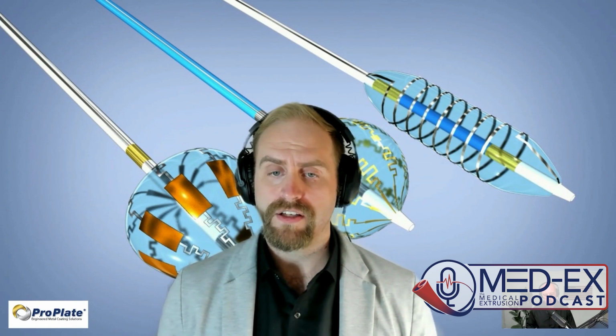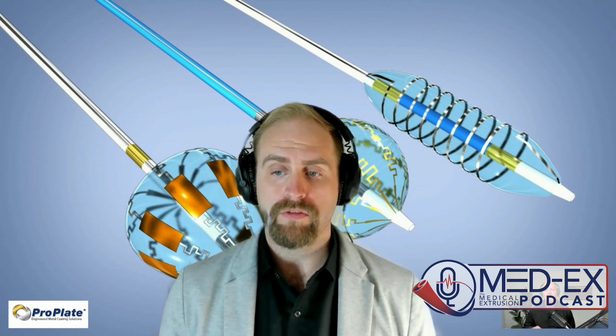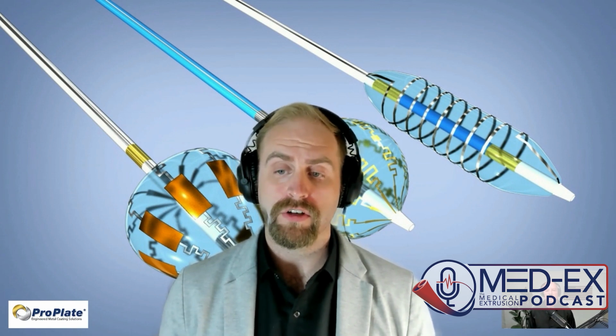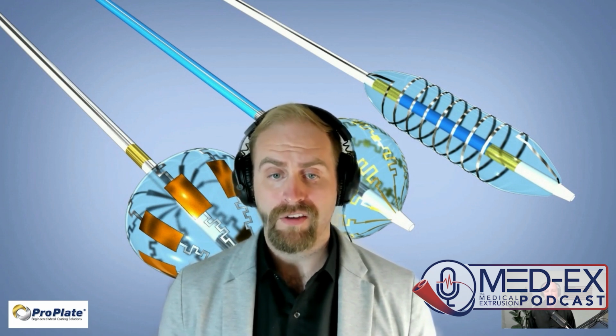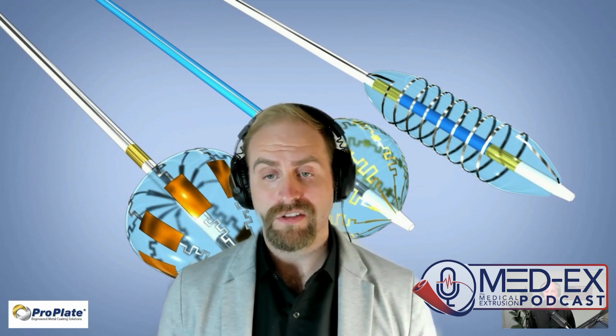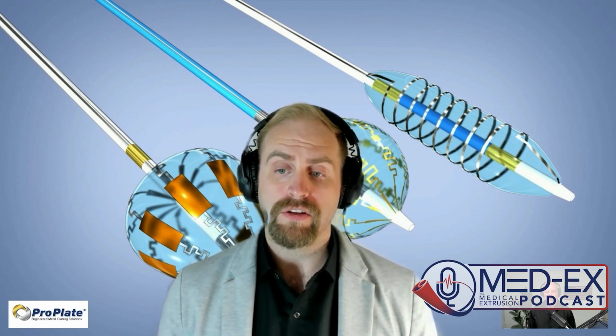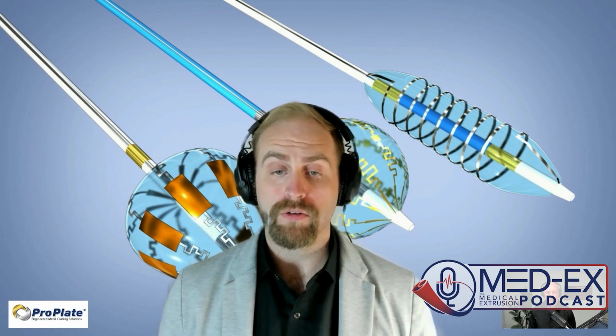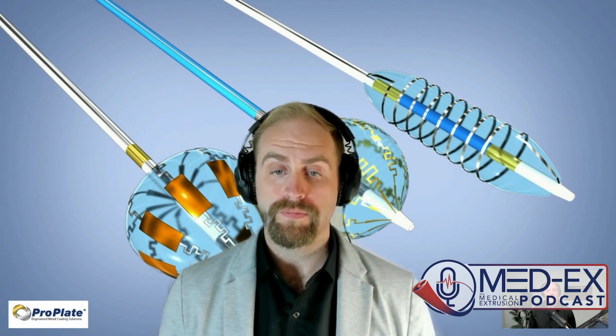It certainly can be. And as I mentioned, if we see a device that needs about 3 discrete marks on it or more, that's where we can be very cost competitive and sometimes be a better cost alternative to traditional marker bands, like you mentioned, swaging, crimping, welding, and sometimes even gluing, which leads you to the next advantage of this technology: the risk of dislodgement is essentially eliminated. This process creates a bond at an atomic level. So it would take enough mechanical force to destroy that component before you remove any of the gold or the platinum from it. Wow.